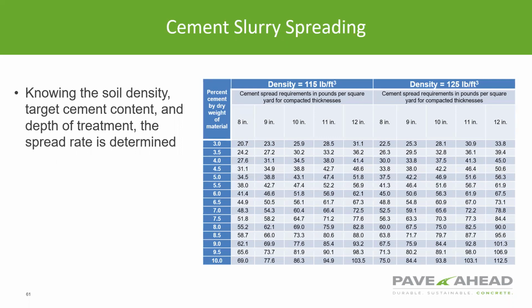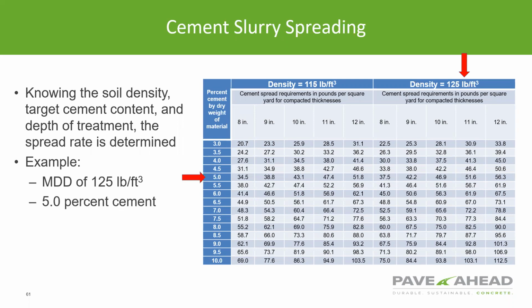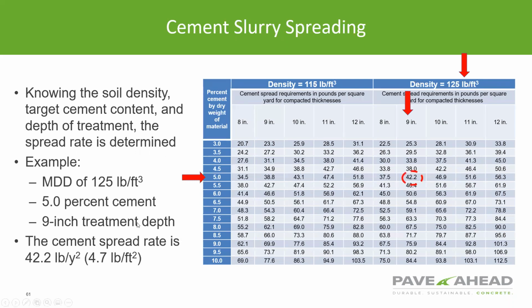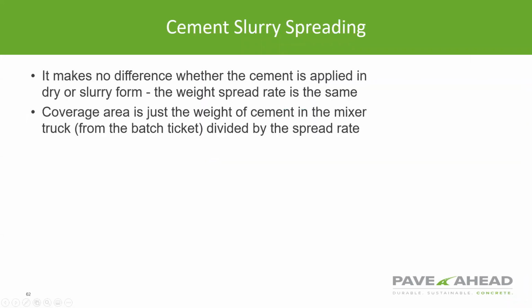This is the chart that we looked at earlier. And just as an example, if we were dealing with a soil with a density of 125 pounds per cubic foot, and let's assume we wanted 5% cement, and we're going to treat 9 inches of depth, then using this chart coming over with the 5% coming down at the 9 inches, we would select a spread rate of 42.2 pounds per square yard, or 4.7 pounds per square foot.